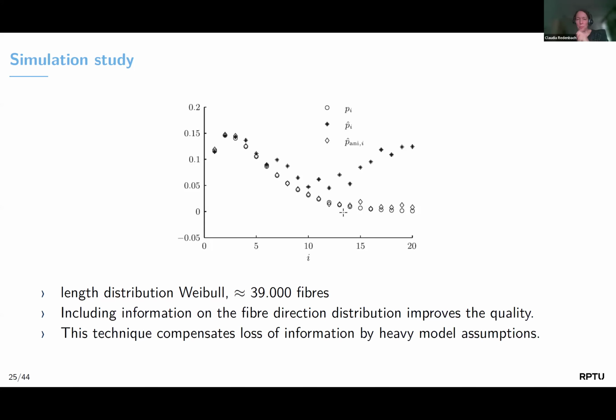Well, from the academic point of view, that's quite nice. And it shows how a high amount of loss of information can be compensated by very heavy model assumptions, and then still you can reproduce information. Unfortunately, on the practical side, we don't believe this to be of too much value because real fiber systems where the fibers are non-overlapping are relatively far away from that Poisson assumption. So therefore, whether this relation between the length distribution and the K function still holds is highly questionable. But for illustration purposes, I think this is a very nice example.